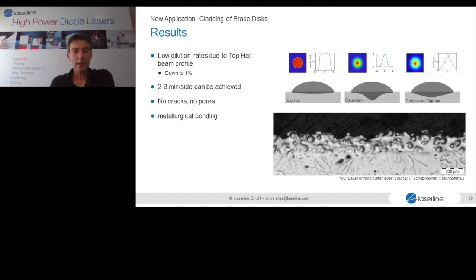To move on a little quicker, some of the results we can show here. So we've seen, as requested, very low dilution. It's down to 1%. And the main reason for this is that the diode laser produces a nice top hat beam profile. You can see from the micrograph on the lower side, the lamellar graphite directly with the clad layer on top. In this case, there's no buffer layer. What is interesting, what's important, there's no cracks, no pores, and we get a very nice metallurgical bonding.